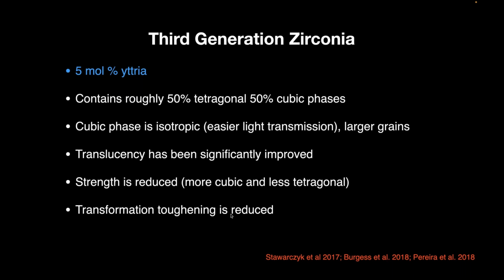However, strength has been reduced in this type of zirconia because the cubic is weaker than the tetragonal, and it has around 50% cubic and 50% tetragonal content in the material. So the transformation toughening is reduced. Some research says it doesn't transform anymore.